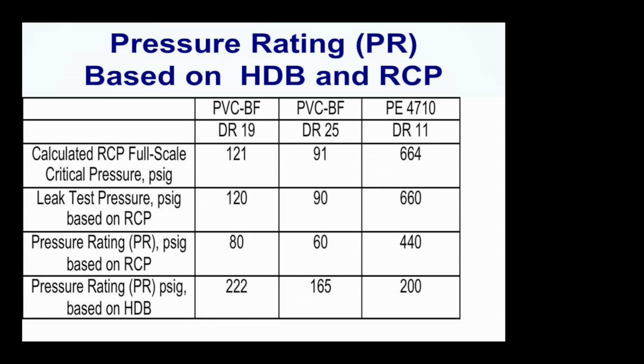So this summarizes what we learned about the pressure rating, and the pressure rating determined by, or really limited by, the full-scale pressure rating by the HDB. For the DR19 pipe that Dr. Lieber's examined, the full-scale critical pressure is 121. That means the leak test pressure should be less than that, let's say 120. If the leak test pressure is 120, then the pressure rating is 80. Considerably less than the pressure rating calculated by the HDB.